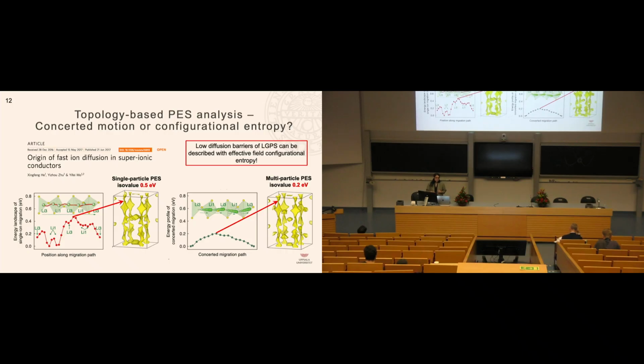And this means that the low diffusion barrier of LGPS and other materials can in fact also be explained by the configurational entropy that we include in our model of the mobile and interacting lithium ions.